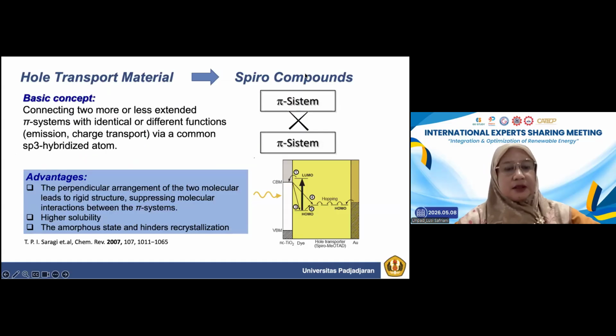And another modification is by using a hole transport material. We use the spiro compound. The basic concept of the spiro compound is connecting two more or less extended pi systems with identical or different function through a common sp3 hybridized atom. The advantage is that the perpendicular arrangement of the two molecules leads to a rigid structure, suppressing molecular interaction between the pi systems. The spiro compound can also have a higher solubility, and because it is in an amorphous state, it hinders recrystallization.